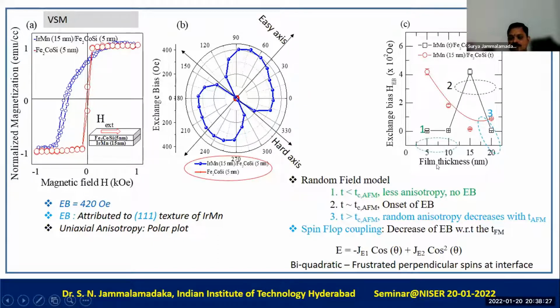We also varied the thickness of the antiferromagnetic layer and the ferromagnetic layer. What we could see is that when we varied the antiferromagnetic layer thickness, initially there is no exchange bias, and all of a sudden there is an exchange bias, and then again it decreases. This kind of behavior is well established, and it has been explained based upon the random field model.